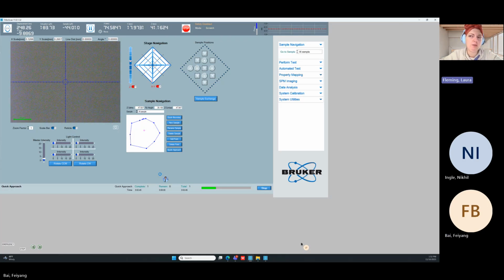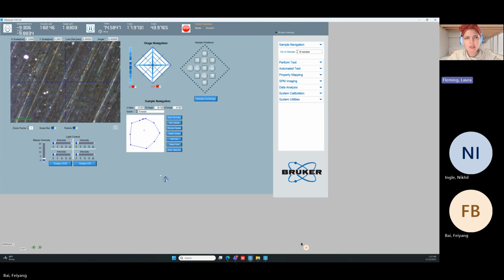Because it did a quick approach, which is completely separate from doing a scratch. If you remember from our discussion regarding the tip to optic calibration, the system needs to have a contact height for the sample, which means the tip has to come into contact with the sample at least once. If it does not, so let's back up. How does an approach work, right? You're looking at the sample surface and you say, go do a scratch here. So it lifts the tip up, comes down, and brings it into contact.